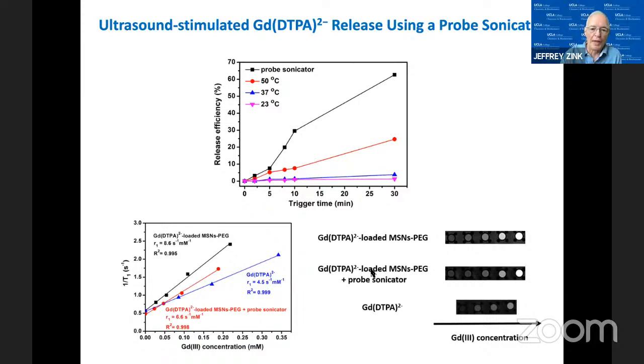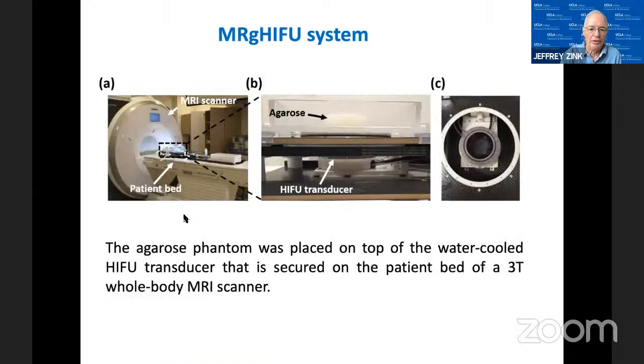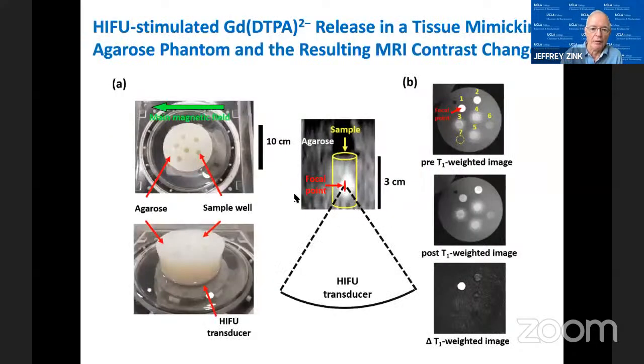We did mass spec to prove that the system is falling apart, and there are some details involving the ultrasound here. As we can see on the right-hand side, here are some MRI images of the effect of our sonication. In this case, we're releasing gadolinium and changing the overall contrast so we can see how much has been released. And it works in the ultrasound system. So again, this is what we do. We place the agarose phantom on top of the HIFU transducer, exactly as it's done with the patients. And then we're using a 3 Tesla whole body MRI scanner. It's a Siemens instrument, and that's the way we do the experiment.